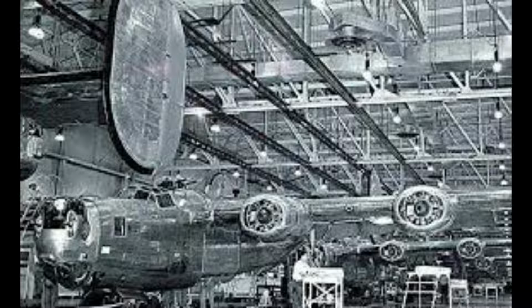The scratches and gouges weren't merely cosmetic. In aircraft structures subject to tremendous stress, surface damage creates stress concentration points where cracks can initiate. An aircraft undergoes constant vibration, temperature cycling, and loading that far exceeds anything experienced by an automobile. The airframe must withstand these stresses for hundreds of hours of flight operation. Surface damage that would be inconsequential in a car fender becomes critical in an aircraft wing spar or fuselage frame. The scratches reduced the metal's fatigue life, compromised its structural integrity, and created potential failure points.